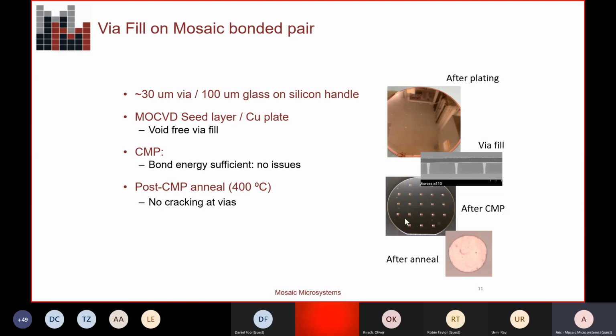And then the next to the bottom picture is the wafer after CMP. So you can see in the top 2 pictures is about a 4 micron overburden of copper after plating, and then we CMP'd that off, and we've had very good success with Axus Technology and also Entrepix in Phoenix for doing the polishing of these wafers.